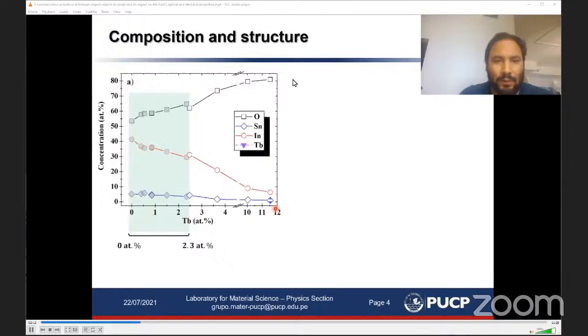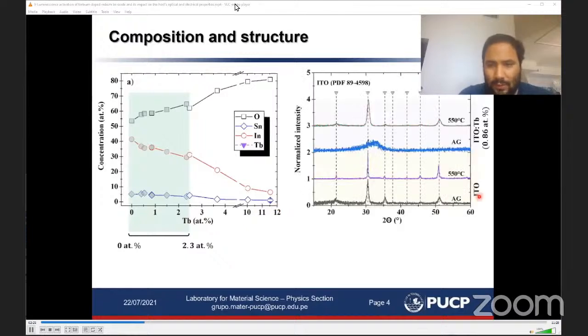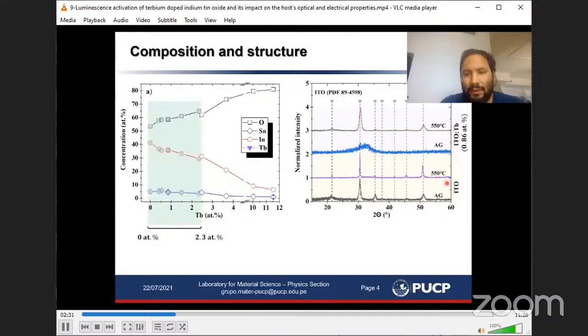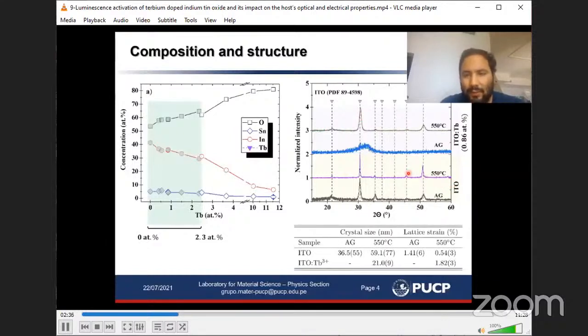After deposition, ITO films grown under these conditions exhibit a polycrystalline structure, whilst ITO doped with terbium exhibit an amorphous structure. After annealing, ITO films increase their grain size, whilst the terbium-doped version crystallized.